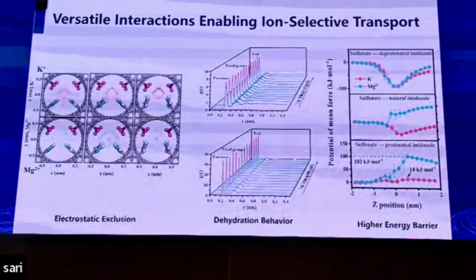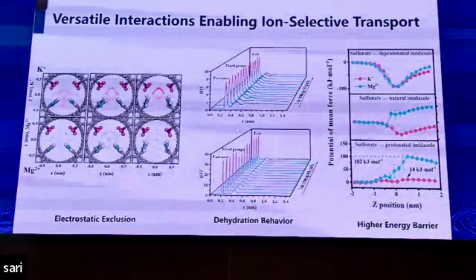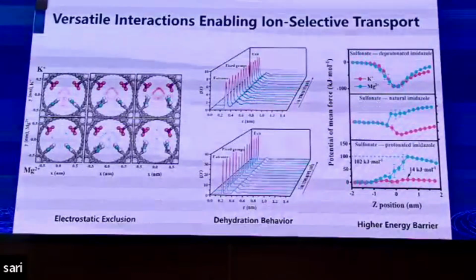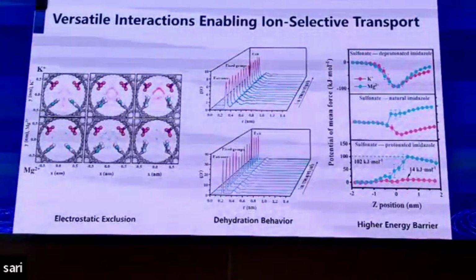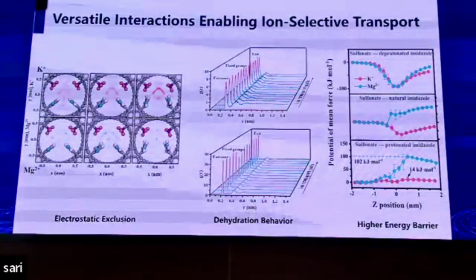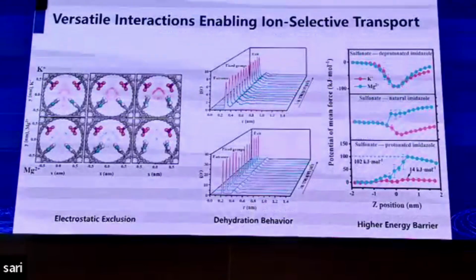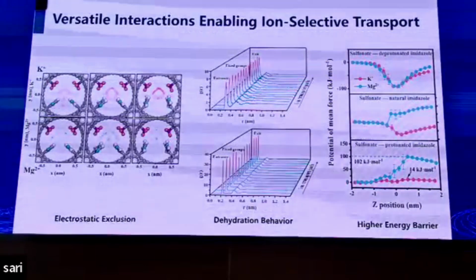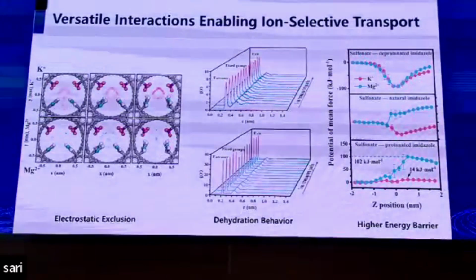And according to the dynamic RDF, if they pass through the pore channels, they will undergo a more severe dehydration phenomenon because they have to overcome larger energy barriers.